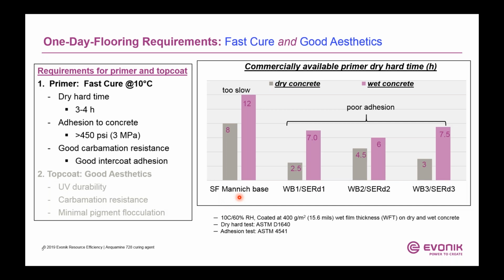On dry concrete, it dries hard dry in 8 hours, and on wet concrete, it takes longer to dry. So on both wet and dry concrete, obviously the solvent-free mannich base is too slow to meet the primer requirement for one-day flooring.